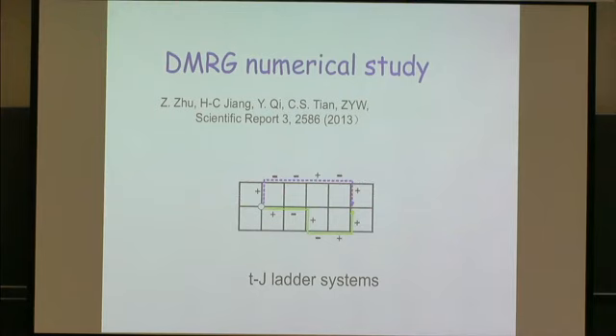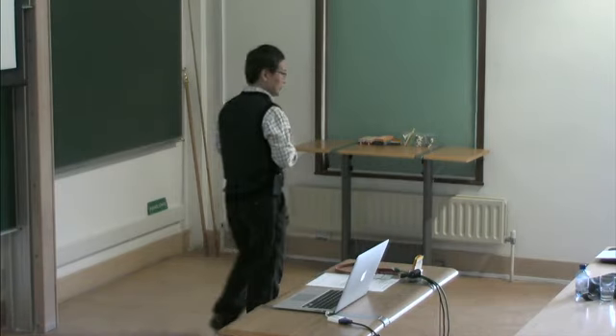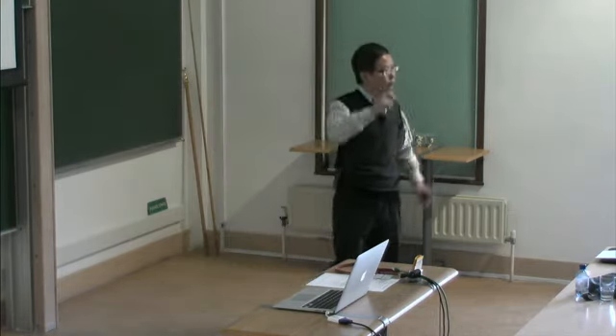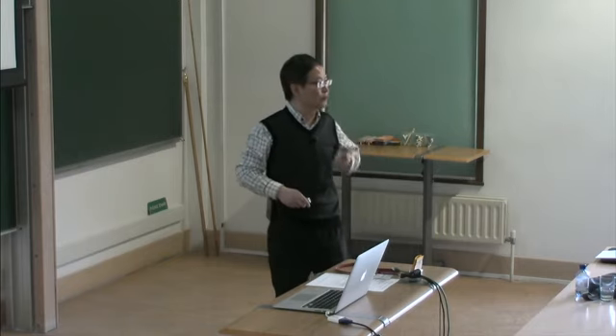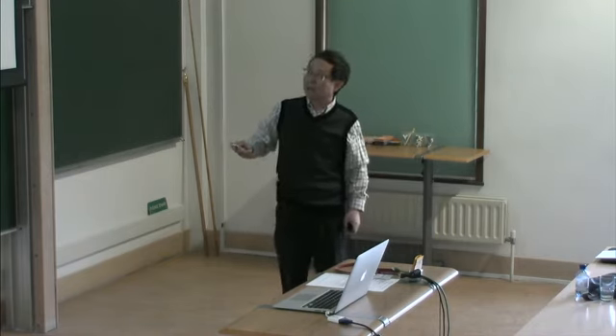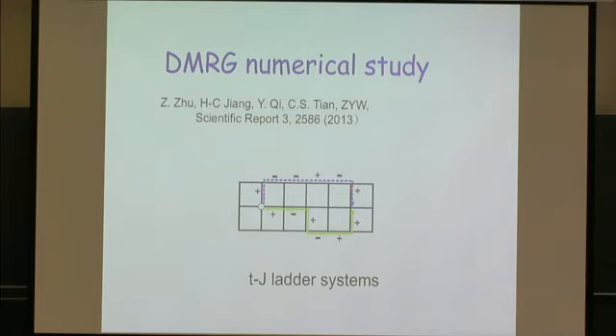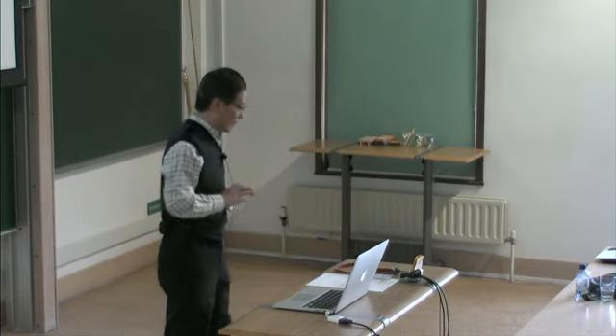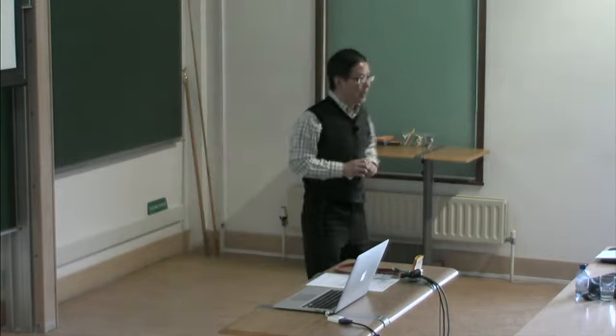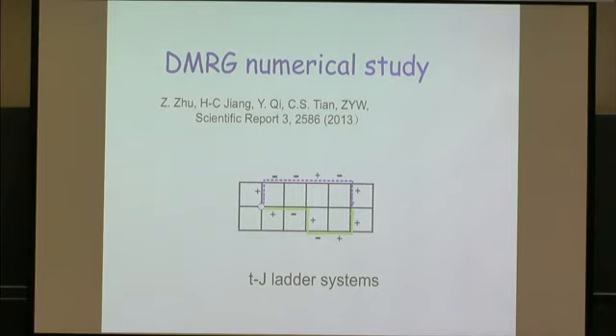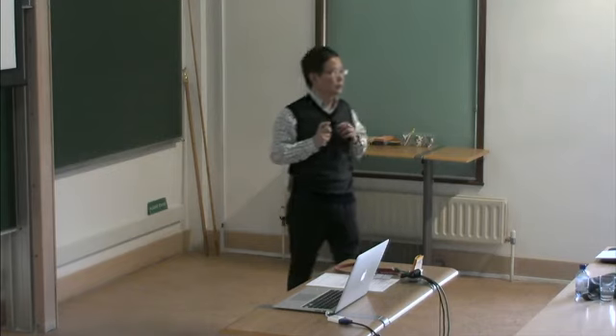So at this point we haven't done any approximation, but as Spear mentioned, we have to sum up all kinds of paths, and this is tremendously difficult unless we find some clever duality transformation. We can treat this system, but we have numerical help to show how this sign structure can play out. And there's a very powerful method called DMRG. It doesn't suffer from the sign problem. But the problem is it can treat a one-dimensional chain very well, or a ladder system with a stack of chains, but it cannot really go to two dimensions for a larger system.